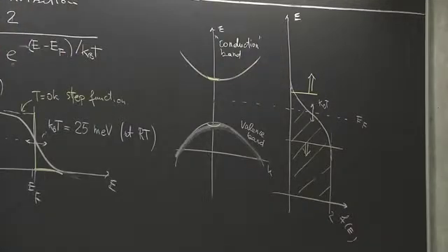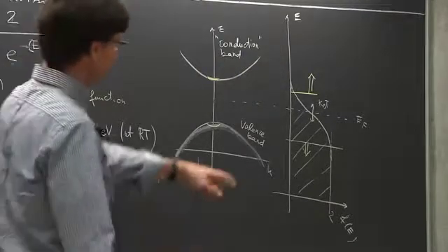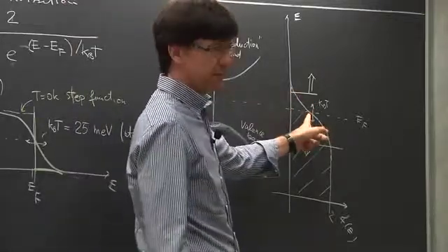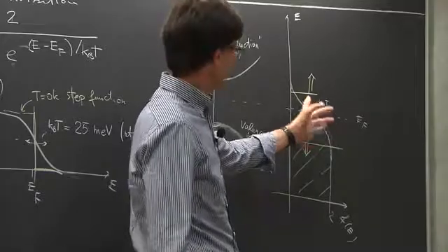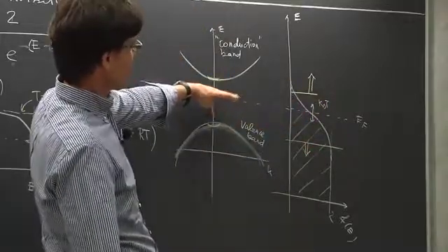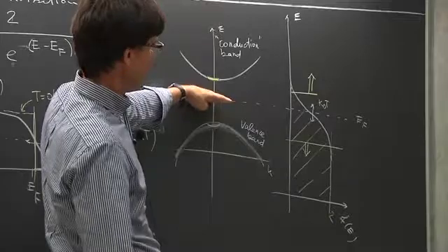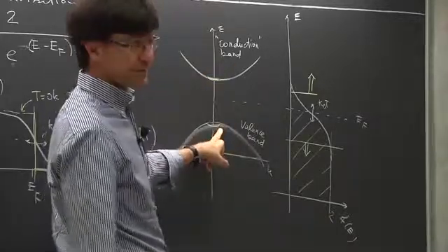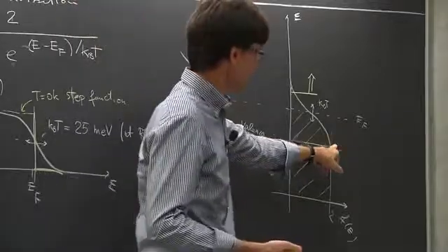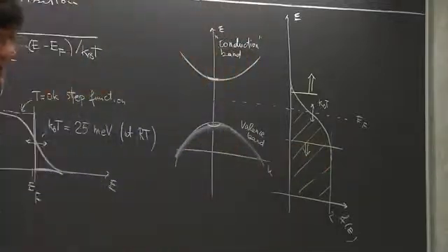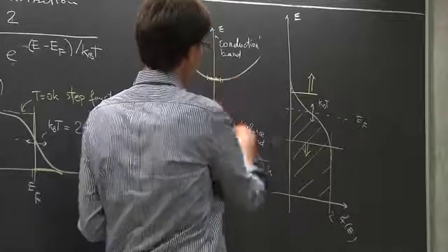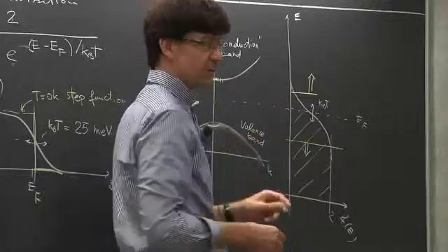Now, you may naively think that the exact point is the middle point, because this distribution is symmetric around EF. So it's quite natural to assume that if I place the Fermi energy exactly in the middle, I will have an equal number of electrons here as deficiency from 2 in the valence band. This is only partially true as an argument, and the reason is that the number of states I have here might be different from the number of available states I have here.